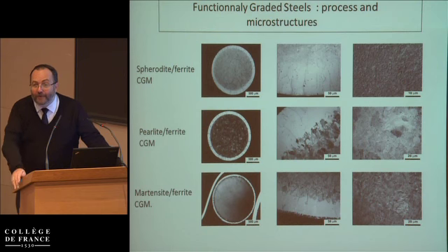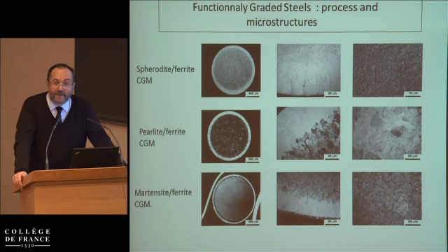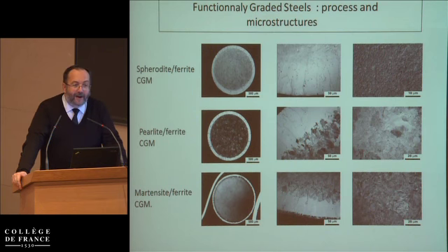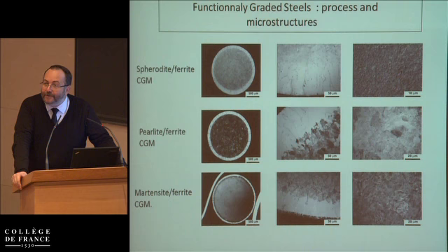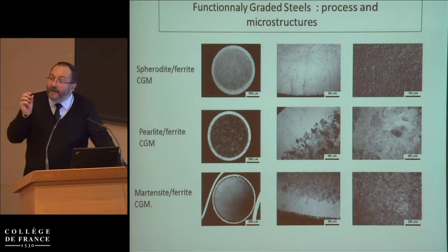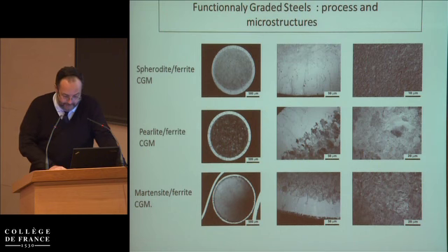Again, we are back to my old friends, the steels. What we are doing here is removing the carbon by annealing the material in argon hydrogenated gas, which is going to remove the carbon, and you have at the surface a layer of ferrite, which is soft by nature.